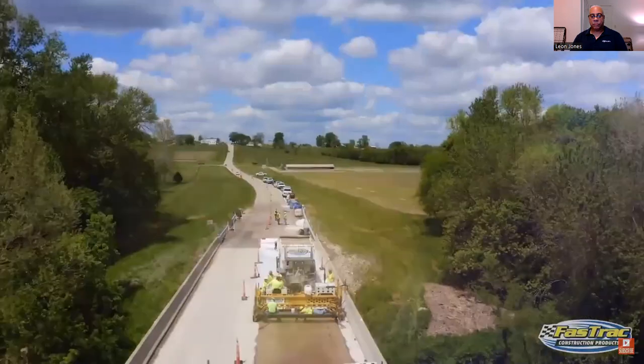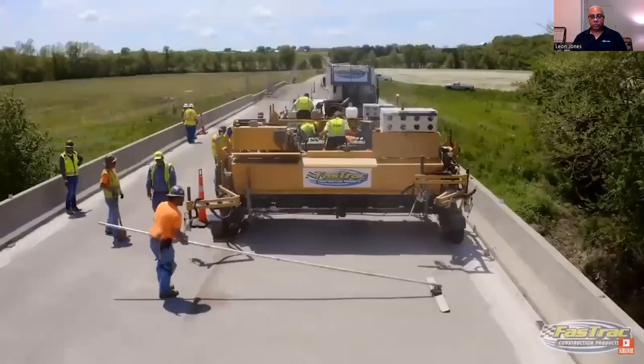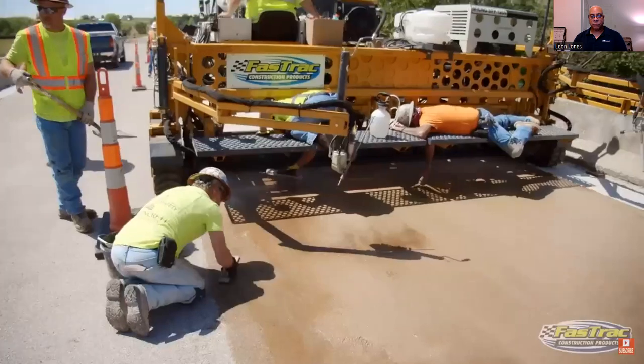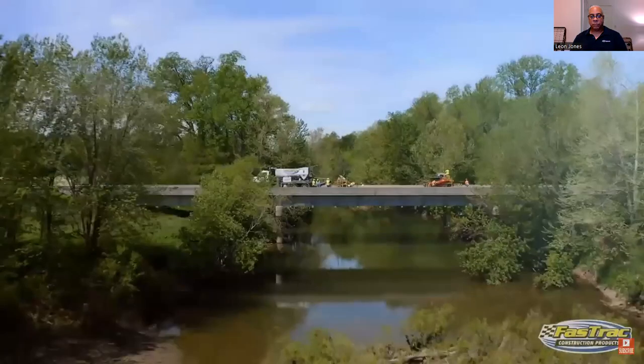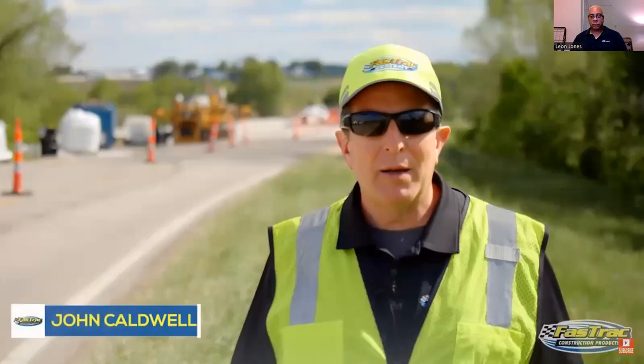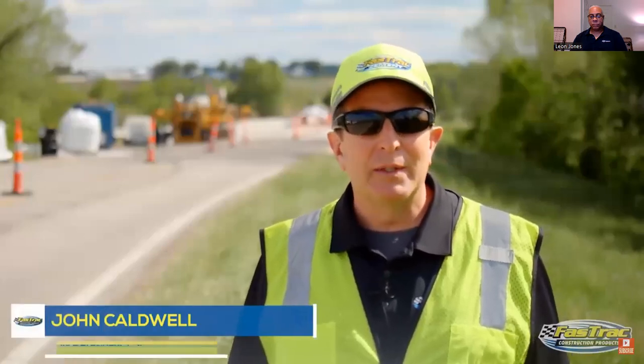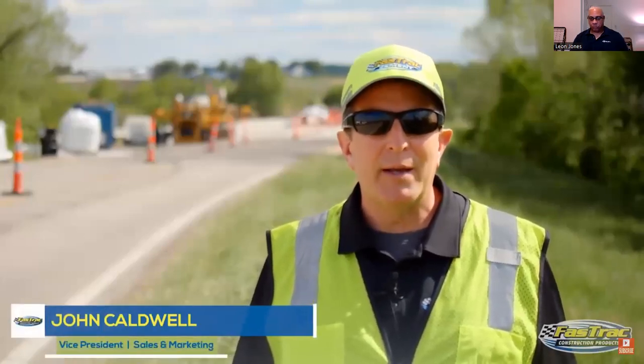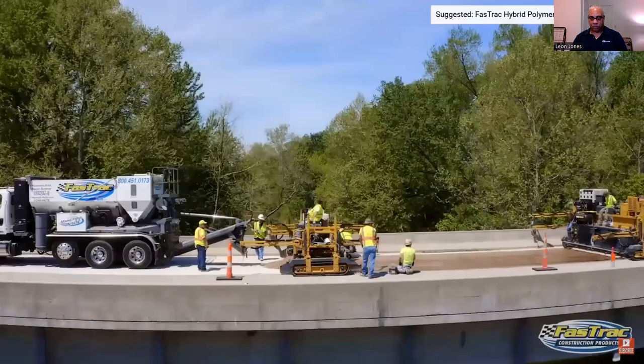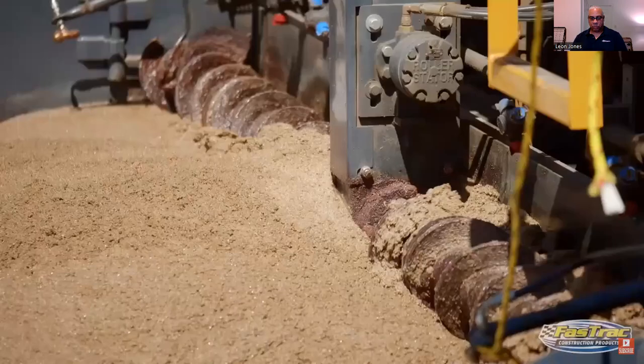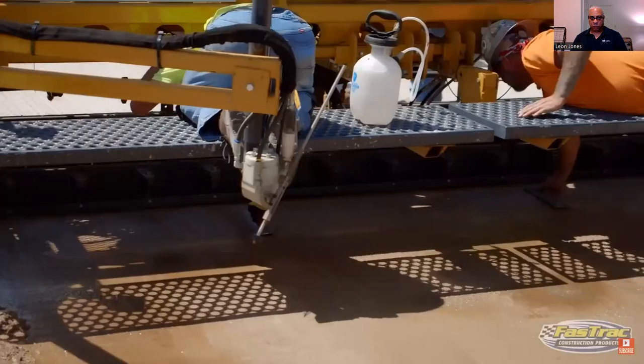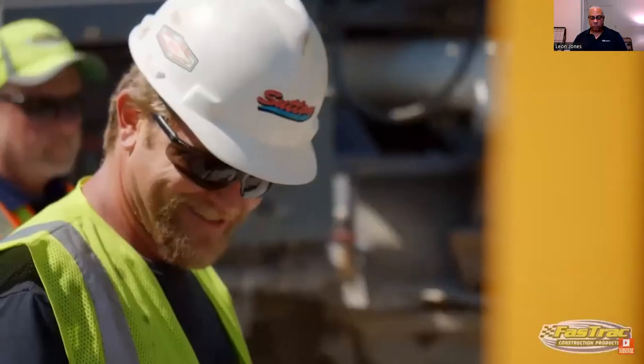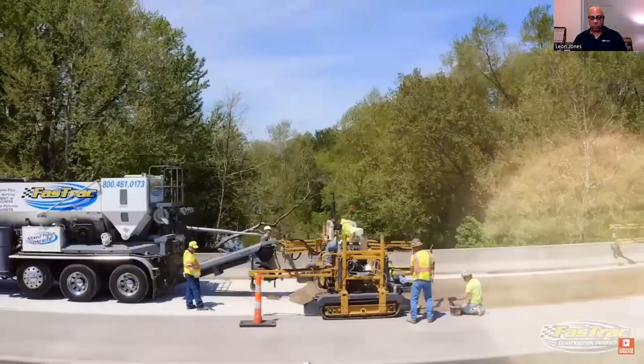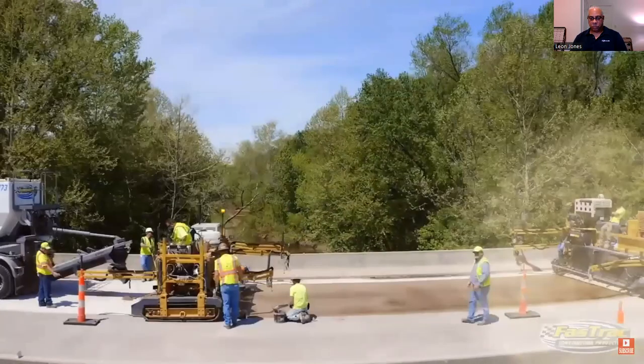We're here today in Franklin County, Missouri, where we just installed our hybrid polymer concrete as a bridge deck overlay on Route Y for the Missouri DOT. The hybrid polymer concrete is a unique material. It's strong like concrete, but flexible like asphalt. It'll carry heavy loads, but also has a high degree of flexibility. It will move with the materials that it's bonded to, whether that's concrete or asphalt. It has excellent bond strength. It's also an impermeable material, so that protects the rest of the underlying bridge from de-icing salts and other chemicals that cause deterioration of our bridges.